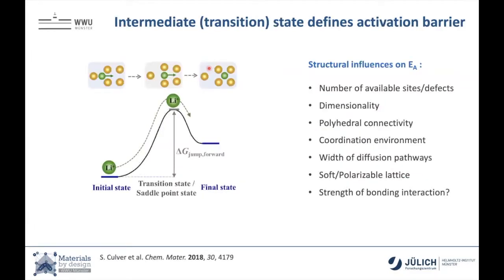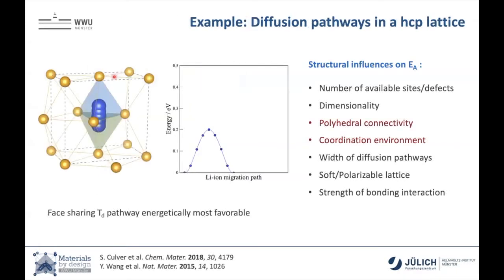What is ion transport? It's a very simple conceptual process where an ion sits on a lattice site, jumps to an empty adjacent lattice site, and displaces the lattice a little bit — all of this costs energy and gives you a delta G. This delta G is measured as an enthalpy activation barrier and controls overall ionic conductivity. The structure itself determines your energy landscape. If lithium is happy in a threefold coordination but unhappy in a fourfold coordination, the final state is higher in energy — meaning even if it overcomes the activation barrier, it's more likely to jump backwards than forwards. Coordination really matters, and so do the number of available sites, defects, and dimensionality.